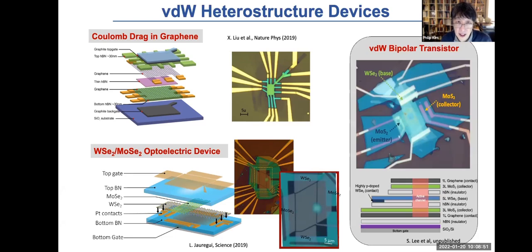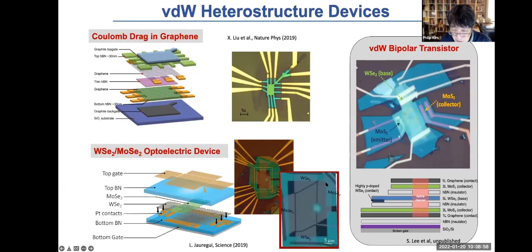You can continue this to make even more complicated devices. In this particular device that I'm showing here, somehow my mouse control is a little bit too sensitive today. In this example, we have a P-type semiconductor, an N-type semiconductor, again touching with an N-type semiconductor, with each layer separated by thin boron nitride, which also has via channels to make the active channels there. Again, it is controlled by the top and bottom graphite gates. You can see there are about nine different van der Waals layers going through the system, and yet each of these electrically active layers gets contacted. This is a good example that one can build rather complicated devices by just stacking. By just designing, you can come up with rather interesting functioning devices, as shown in this example.